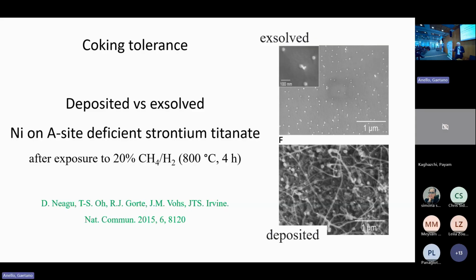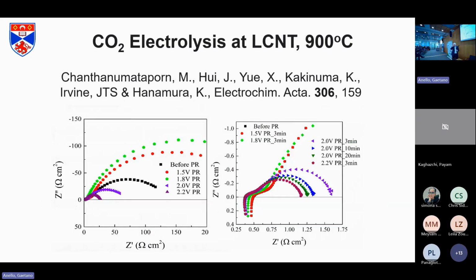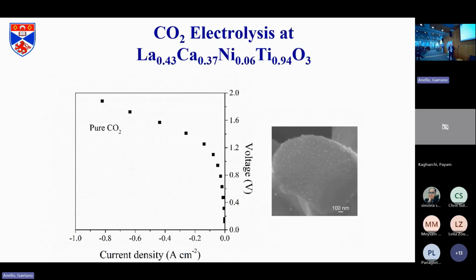So these look like good candidates for CO2 electrolysis, and here you are using 2 volts, 2.2 volts to drive the process. You get a big reduction in the electrochemical resistances, and you produce quite an effective electrode. So here you have nanoparticles, and you're doing the electrolysis in pure CO2. There's no sweep gas. You can't do that with a nickel YSZ electrode, and you get conversion of CO2.